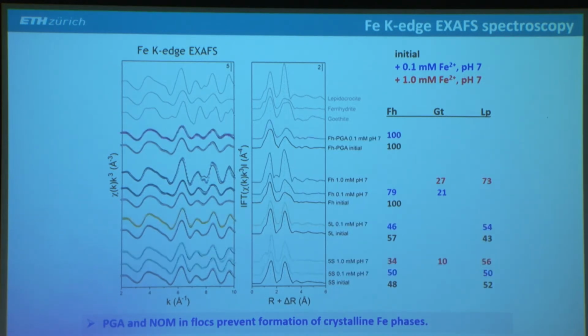We do the same with the ferrihydrite coprecipitate with polygalacturonic acid. There's no change. We still have the ferrihydrite at the end. And in the flock samples, this is shown down here. You can look at the linear combination fitting results. Of course, we have ferrihydrite and lepidocrocite present initially, but there's not so much change. Maybe in the highest spiked iron concentration, pH 7, there could be some goethite formation and maybe some lepidocrocite formation, but it's much less than for the pure ferrihydrite.